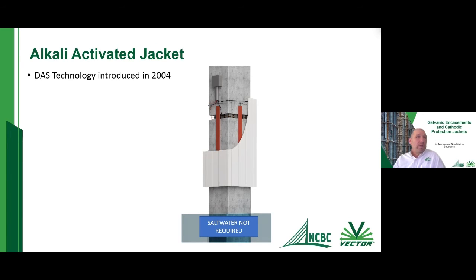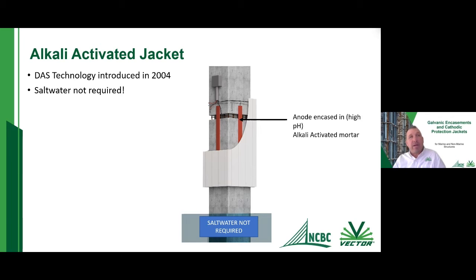So what this technology is basically, it's very similar to the Tidal Plus jacket, but it's called a distributed anode system. It's an alkali activated jacket system, and it does not require salt water. It has an anode very similar to the Tidal Plus anode, but instead of being encased or surrounded by a wicking fabric, it's actually encased in an alkaline mortar. So it's encased in a very, very high pH mortar, very similar to how a AA battery in any of your remotes that you would use for your TV works. The zinc shell is basically encased in a high alkaline activated mortar to keep that zinc shell in an activated state.